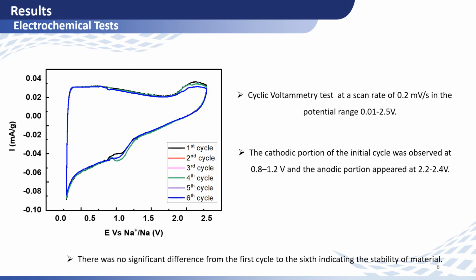Concerning the electrochemical tests, cyclic voltammetry is performed at a scanning rate of 0.2 mV per second. We can notice a cathodic portion at 0.8 until 1.2 volt, while an anodic portion appeared between 2.2 and 2.4 volt. We didn't notice any significant difference from the first cycle until the sixth, which indicates the stability of this phosphate material.